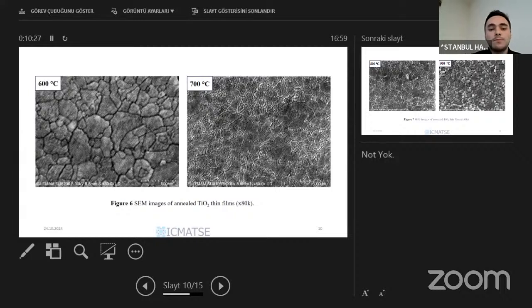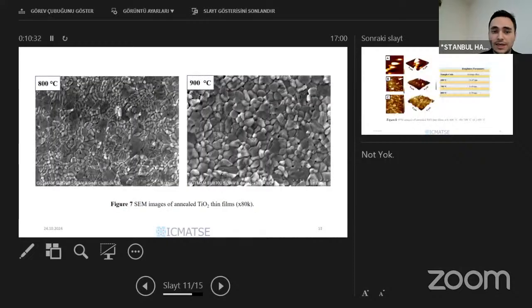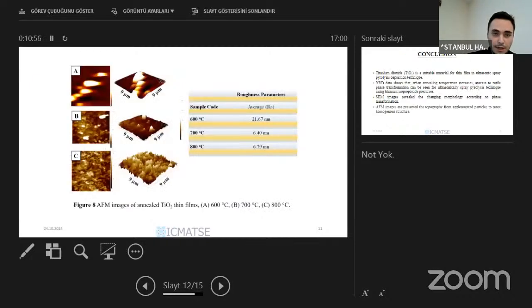At 700 degrees it's similar, but the grain size decreases slightly. We can see this much better at 800 and 900 degrees, where our grains turn into particles, and especially at 900 degrees we have squeezed particles on the surface, as seen in the SEM images.